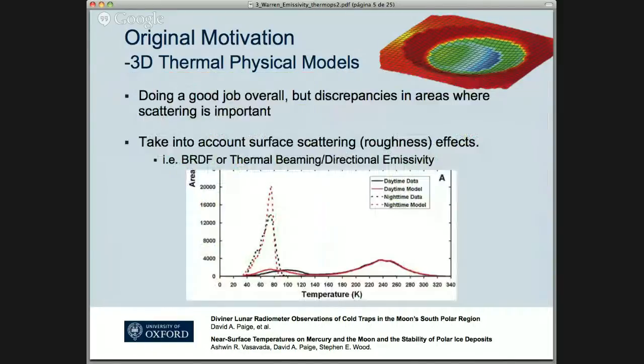What we think is going on here is that there are surface scattering effects, particularly in the thermal infrared, that the model is not taking into account. Currently, the model just assumes isotropic scattering, which is probably incorrect.